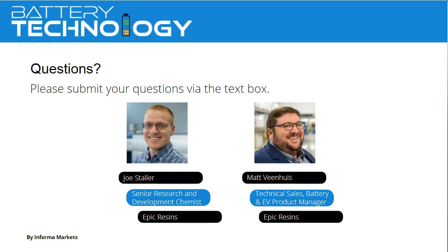Single-component epoxy systems, now those vary. Generally, those are formulas where the chemistry requires refrigeration, and those range anywhere from 1 to 2 months to 3 months in refrigerated storage. However, Epic Resins also has single-component chemistry that can be stored at room temperature, and we have 10-month shelf lives at room temperature on some of our single-component chemistries that have excellent adhesion and really great high TGs as well. So we have quite a variation of shelf lives depending on your needs.